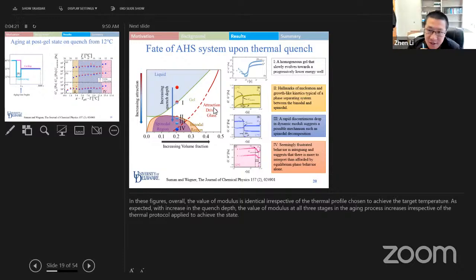Yeah, sure. Following Shin's question, I think another challenge is that in the experiment they're using coating of the nanoparticle surface, and this actually is not a hard sphere. For hard spheres we actually know how to model the interaction force between the spheres, but if you consider this soft, coated surface, how to describe the soft interaction is another big challenge. Nobody knows what the interaction between soft surfaces looks like. I think 20% volume fraction is not a big challenge for computation, but how to reasonably model the soft interaction would be a huge challenge for the modeling part.